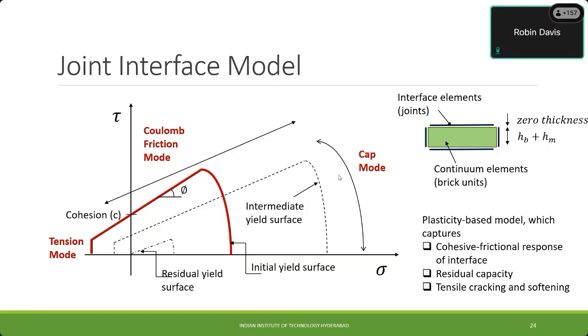So these wall tests, isn't it difficult? Wall tests are actually notoriously difficult to perform. So we got hold of data from other countries. The only problem was that in most of the tests coming from other countries, the brick was invariably stiffer than the mortar. But we were able to find a few tests where they had used weaker bricks, and those are the ones we used to calibrate our model.